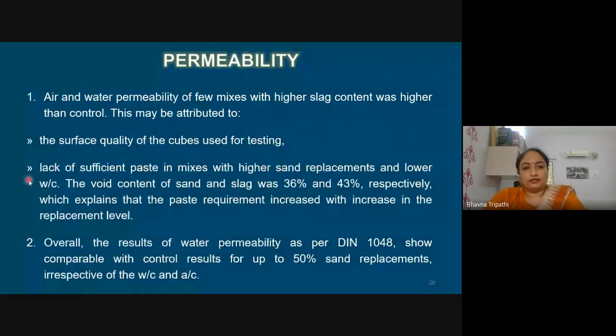Another reason is lack of paste, and the lack of paste was evident because the void content of sand and slag were different. We had tested the void content of pure sand and pure slag separately as per ASTM, and there was an appreciable difference. The void content of slag was 43%, however that of sand was 36%. So this was another reason.